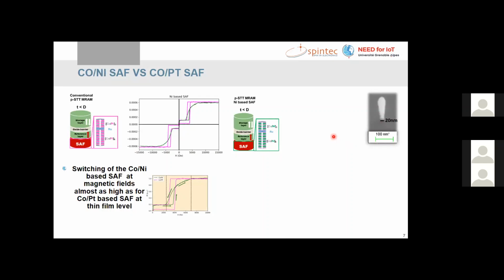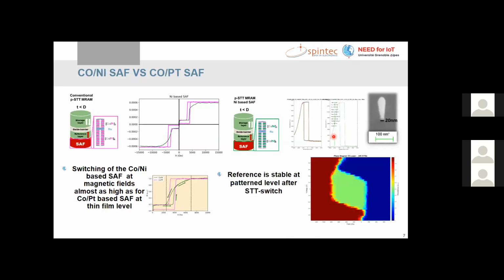And after making the device itself and the contacts, we have some electrical results showing that the reference layer is stable, not switching after applying a magnetic field, and even after applying some voltage that will produce the spin transfer torque switch that is typically the writing mechanism of STT-MRAM. So also we have a low stray field and a stable state at zero field, which is required.